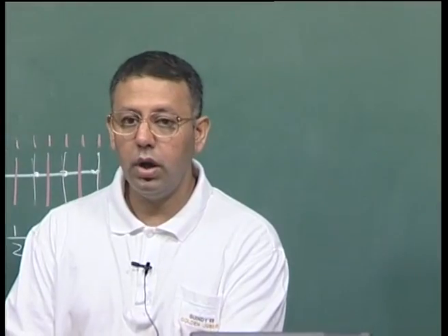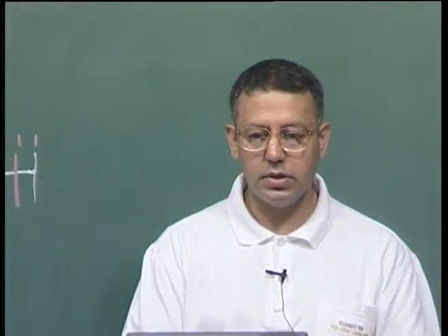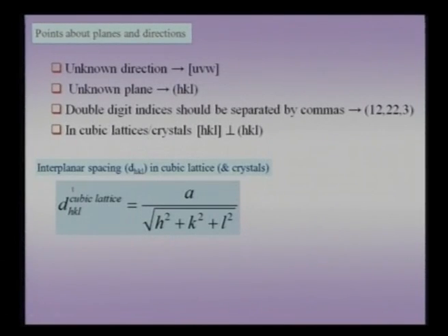This also brings us to another point, perhaps not often discussed: I have 3 indices in 3 directions. As you know from the cosine law, there is actually an equation connecting the 3 indices. That means 2 independent indices would have sufficed in 3 dimensions. So when you use 3 index notation, as we do in Miller indices, there is some extra information that this third index is giving us. What is that extra information? Embedded within my HKL planes is also the interplanar spacing.